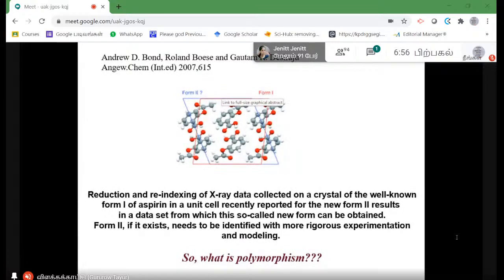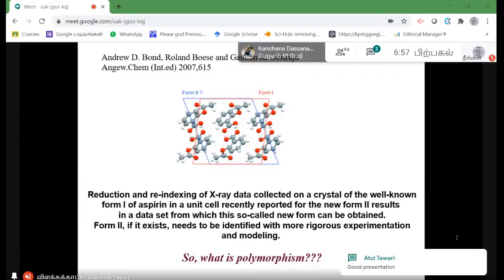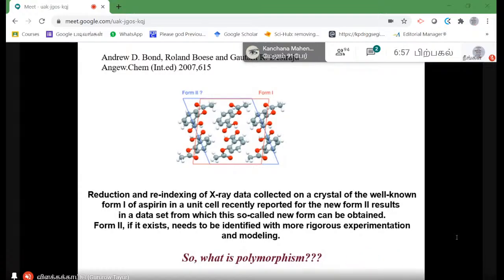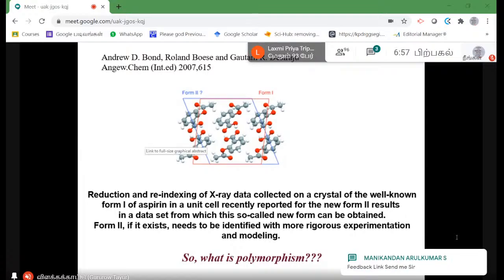So crystallography can therefore sometimes be a very challenging technique to use. In this particular case, they showed that reducing and re-indexing X-ray data collected on a crystal of the well-known form 1 of aspirin in a unit cell recently reported for the new form 2 results in a data set from which the so-called new form can be obtained. That means form 2, if it exists, needs to be identified with more rigorous experimentation and modeling. Though they showed basically that the two different forms, 1 and 2, are one and the same.